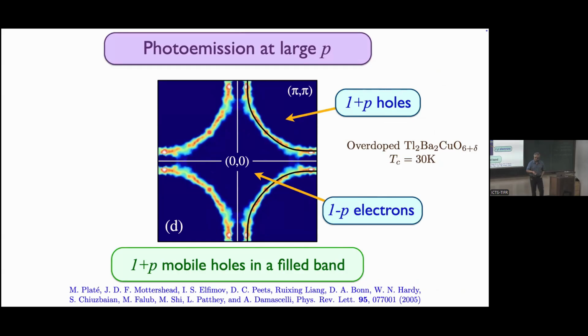One is that if you're on the overdoped side, then you see a beautiful Fermi surface of a single band. And if you count up the area of the Fermi surface, it's exactly what the Luttinger theorem would require. So the Luttinger theorem would say at doping P, there should be a Fermi surface of size 1 plus P, because 1 is for the half-filled antiferromagnet and P is the doping. And that's exactly what you see.